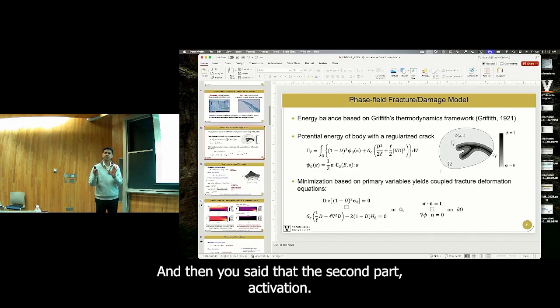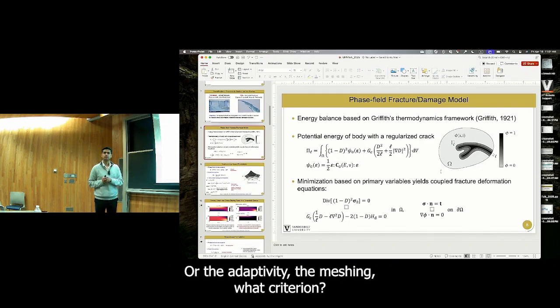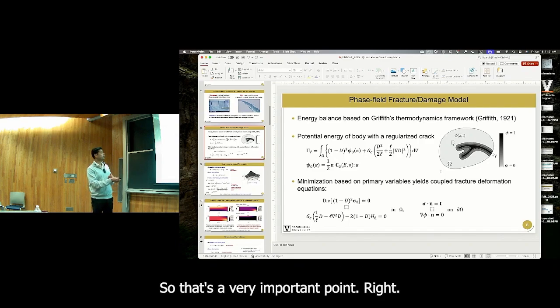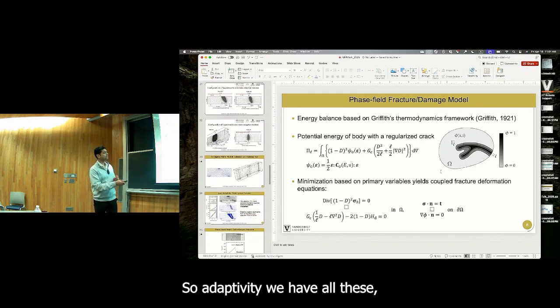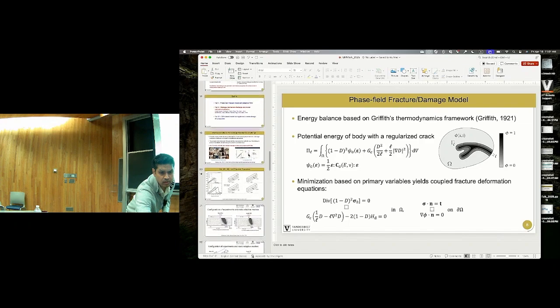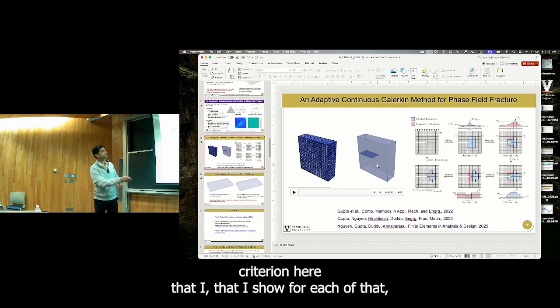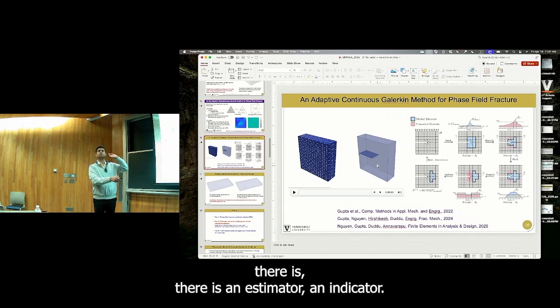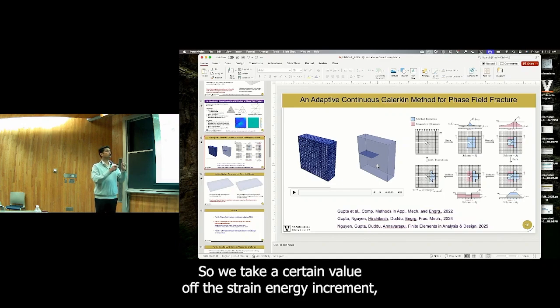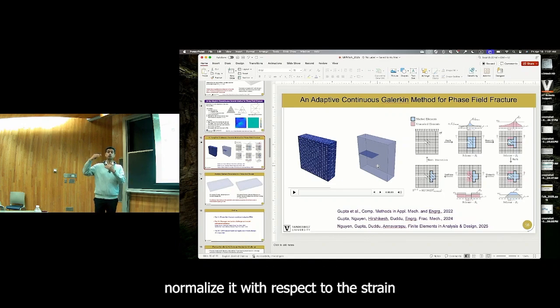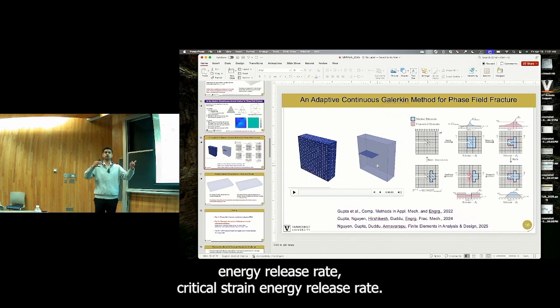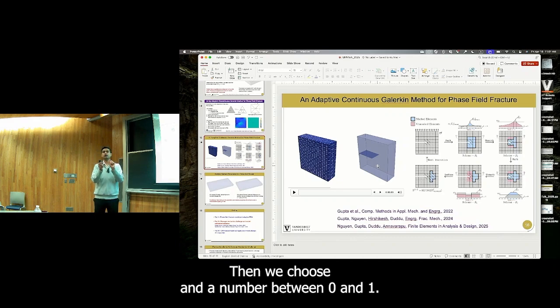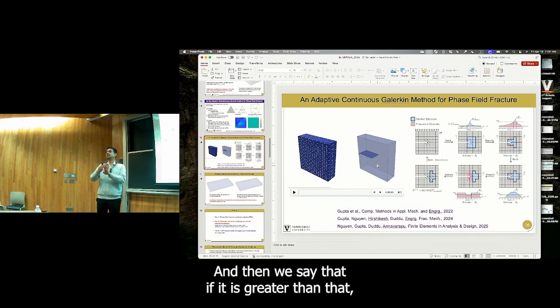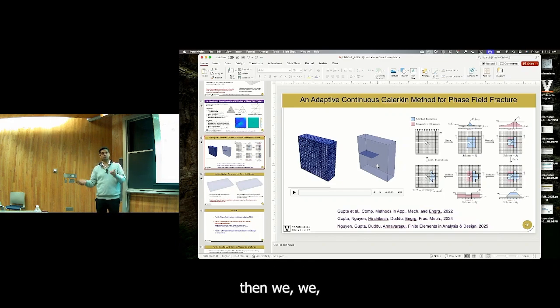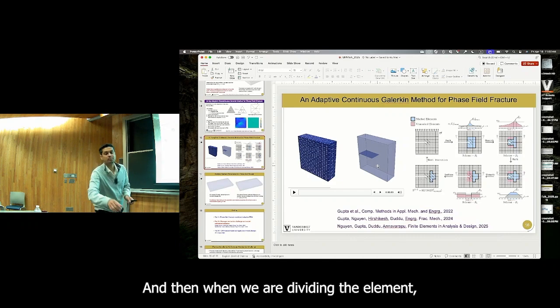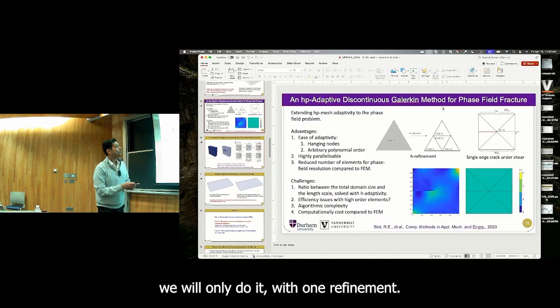And then you said the second part, activation or? The adaptivity, the machine, what criterion? Oh, adaptivity, yeah. So that's a very important point, right? So adaptivity, we have all these criterion here that I show. For each of that, there is an estimator and an indicator. So we take a certain value of the strain energy increment, normalize it with respect to the critical strain energy release rate. Then we choose a number between 0 and 1, and then we say that if it is greater than that, then we divide the element.